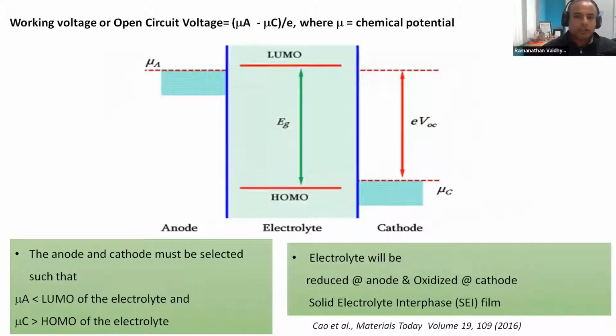And so one of the things we look for is charge storage. And one key thing for charge storage is shown in this very simple diagram, where you have an electrolyte which decides the potential window of operation. And also you have the chemical potentials of an anode and a cathode. Now you have to have these chemical potentials, or the energy levels, of the anode and the cathode match the electrolyte in a very precise manner to be able to get very efficient charge storage. For example, if these energy levels are not exactly positioned, you may get what is called a solid electrolyte interface, which is an irreversible chemical reaction by which you might increase the resistance of your charge storage device, which is very unacceptable.